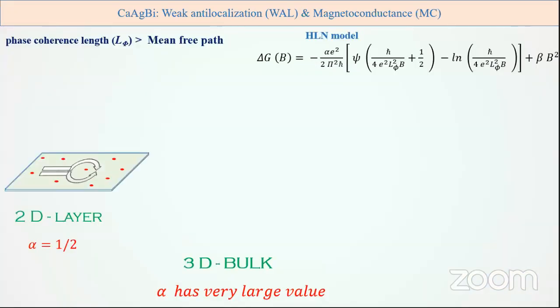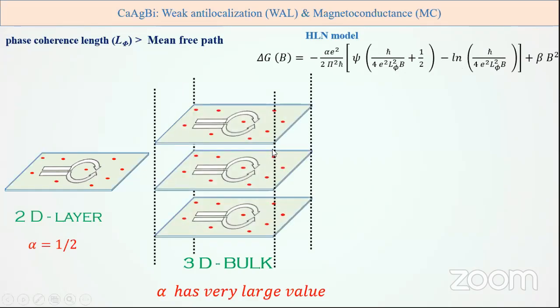So for a 2D system, one charge carrier path is coming in this direction, and the other charge carrier path is coming in this direction, and they get interfered due to this large phase coherence length. While they scatter, this kind of weak anti-localization property can be seen. This can be explained by the Hikami-Larkin-Nagaoka model, where the first term comes from the interference term, and the second is due to the cyclotron orbit term. For the 3D bulk limit, we can think our system is a 3D system, but still we can see this weak anti-localization. This system can be considered as a large number of 2D parallel conduction channels, where the phase coherence happens in each parallel conduction channel and gives us this weak anti-localization property.